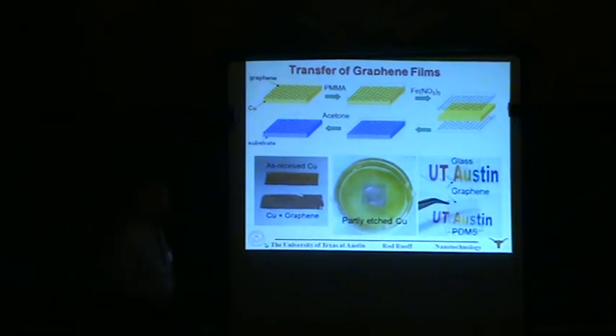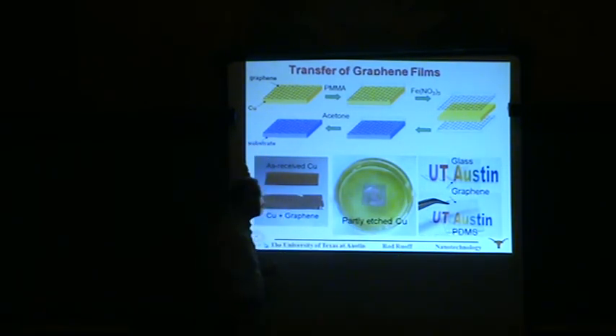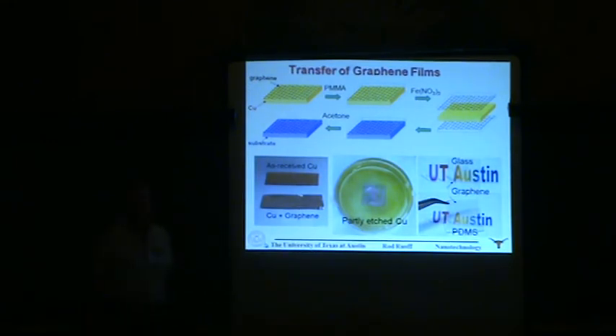But with that approach, you can then transfer the graphene to substrates like glass or PDMS polymer, and you can dissolve away the polymer that you used, like PMMA, with acetone. There's always some residue that causes problems in terms of electronics and so on. So there are a lot of challenging processing issues to get back to pristine graphene that might be needed for certain fundamental studies or for applications.